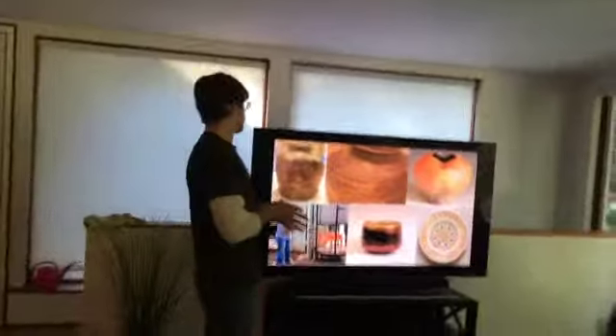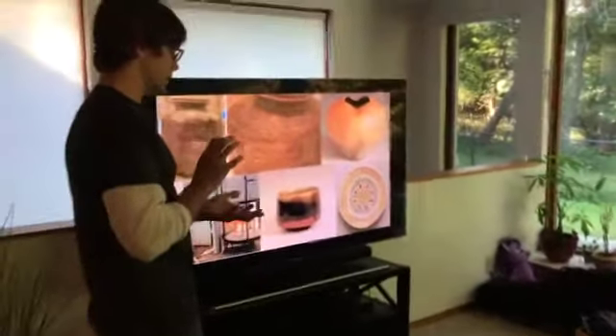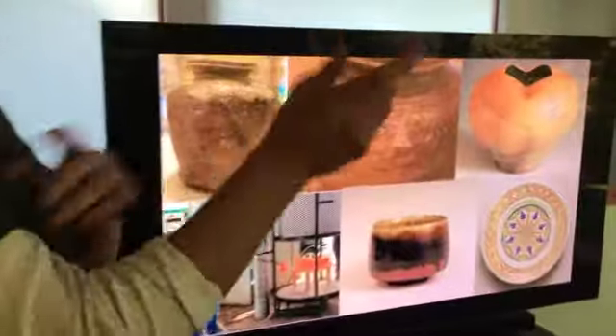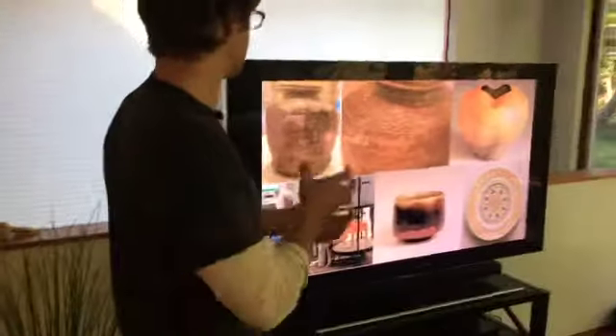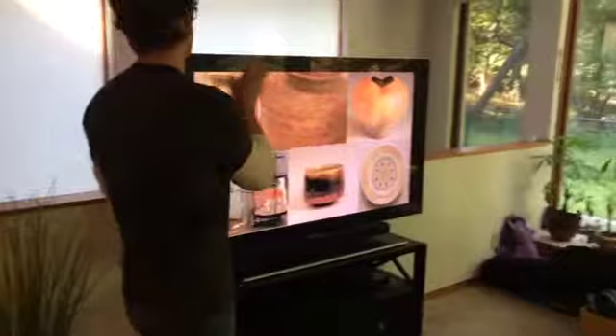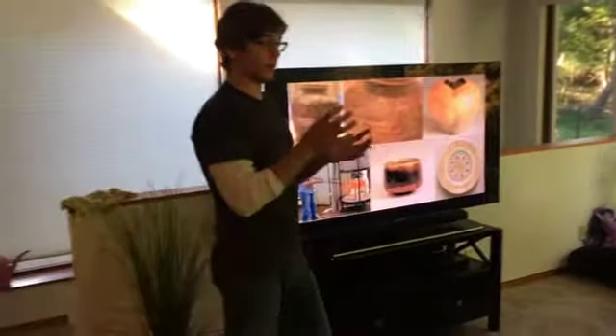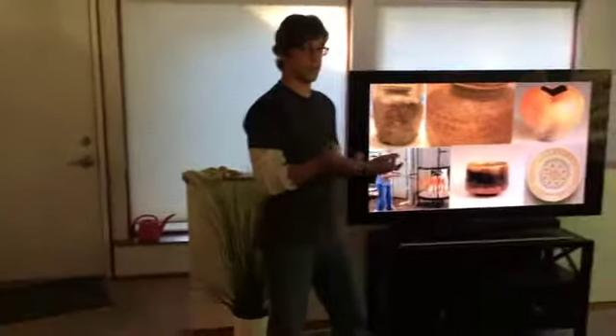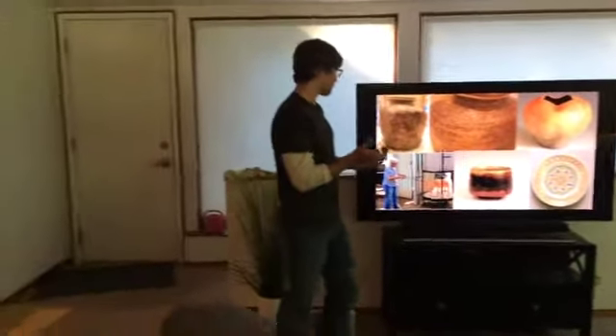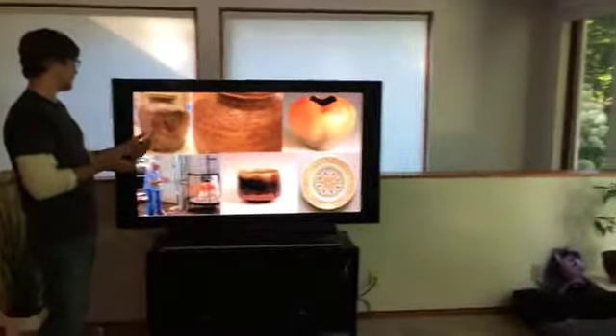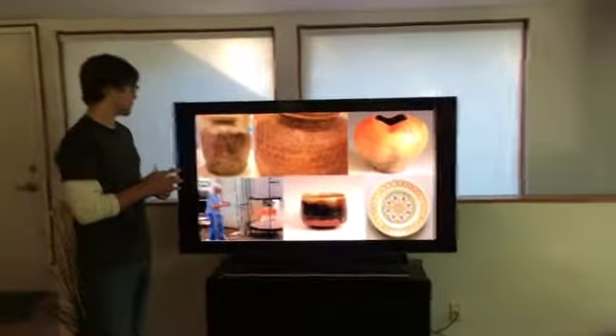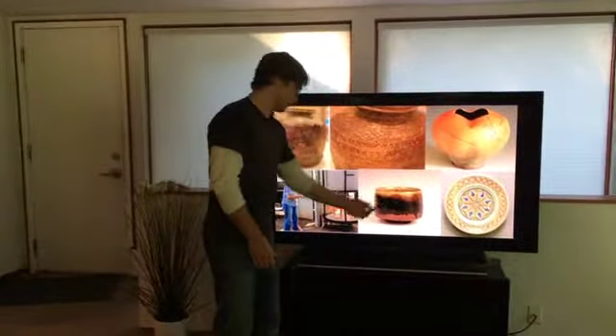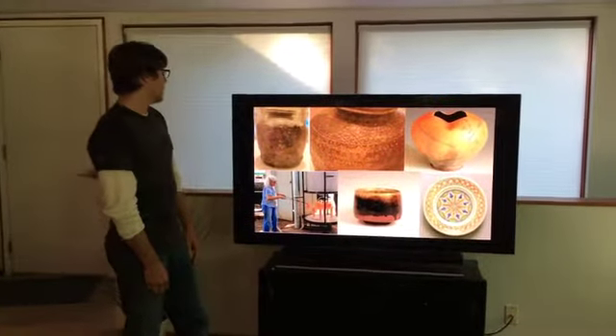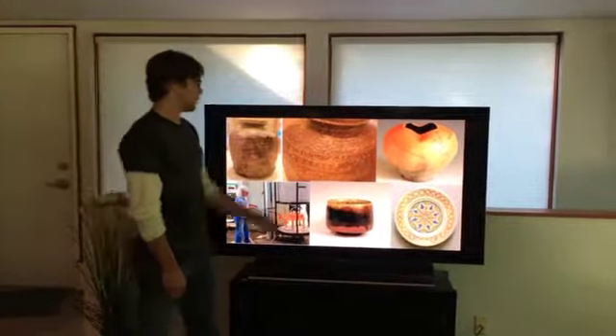So when the wood is fired in the kiln, what happens is the wood burns up, turns into ash, and the ash is flying around the kiln. And ash contains potassium carbonate, and in this particular case, the potassium will attach itself to the pot and create sort of a pseudo glaze with the silica, forming potassium silicate, which is a glass. Tends to be rougher in these cases and not as glossy and nice as you would see later or with modern low-fire pots like this. Next style we'll have is raku firing.